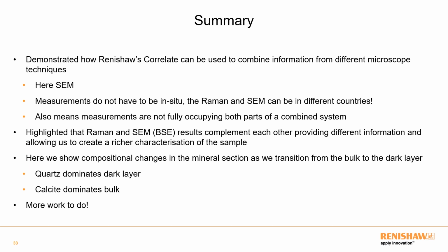From this specific example, I've highlighted that the Raman and the SEM results actually complement each other and provide different information about the sample, and they let us build together a richer characterization of the sample. Specifically, we've looked at the compositional changes in the mineral section. So as we transition from the bulk to the dark layer, there are clear differences. The dark layer, this dissolution layer, is primarily quartz based, and the bulk of the sample is primarily calcite based. There's a lot more work here to basically understand the sample in more detail, but I think we've made a good start, and perhaps the next best thing would be to try a different technique to try and learn a little bit more about the sample again.